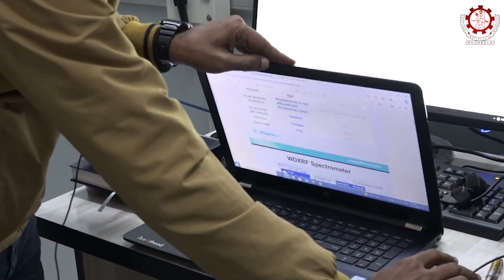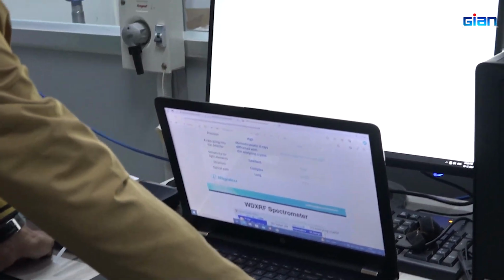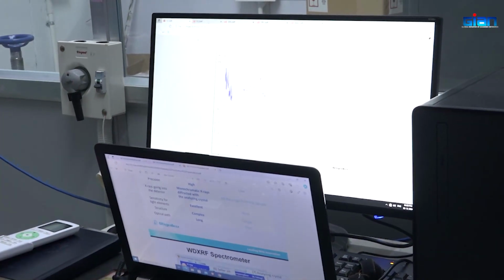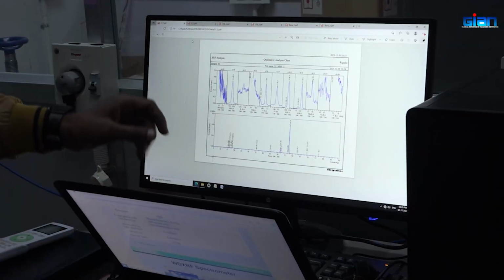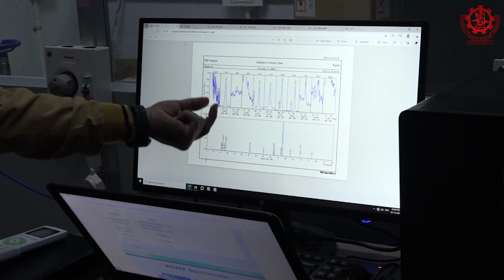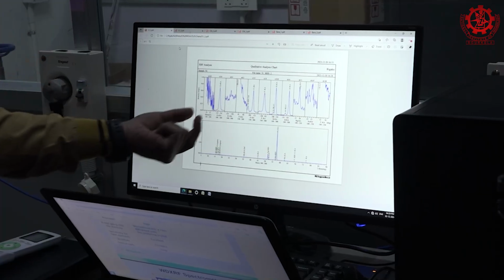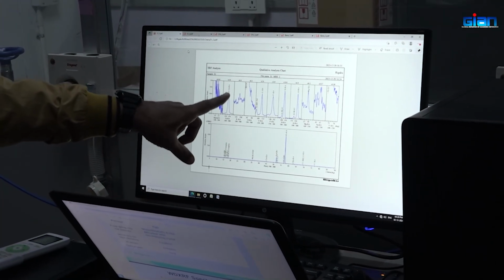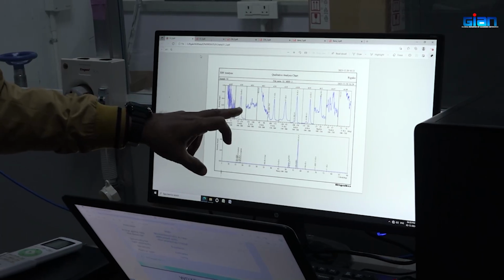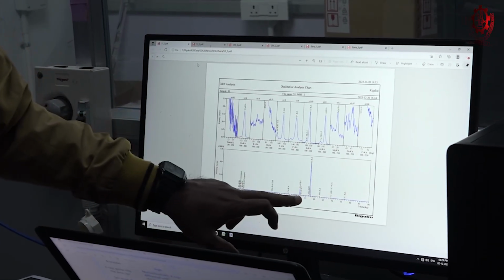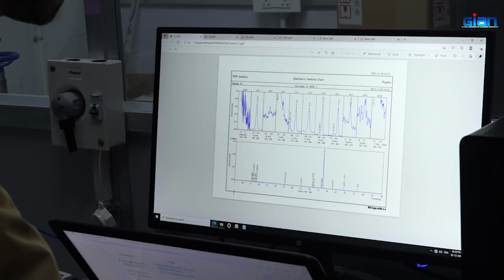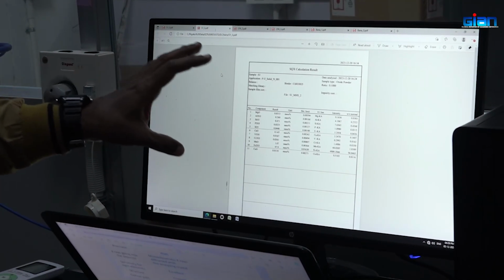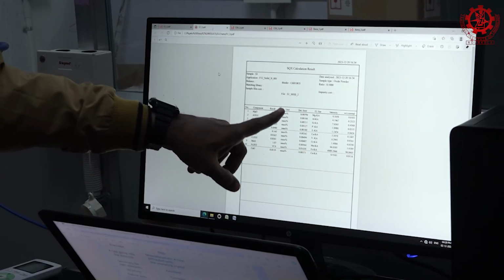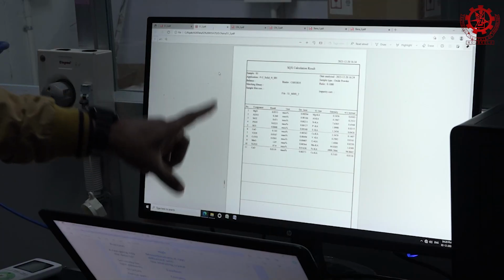You can see from the data, this is an iron ore sample, and this is a qualitative analysis chart. You can see different curves, different scales. This is a 2 theta scale, and this is an intensity scale from calcium, and this is Ka, which means K alpha. This is for calcium, this is for potassium, this is Si, this is aluminum. But here it is a combined graph, and we will get a third set of data. That is the quantitative result. You will get the mass percentage of these components in oxide form.